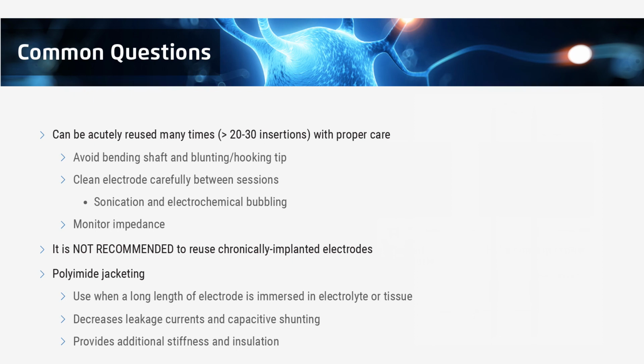Another benefit of electrochemical bubbling is it allows you to detect things like short circuiting as well as insulation damage. It's important to note that any exposed metal within the electrolyte that's subjected to this potential will create electrolysis. Thus, if any bubbling is seen anywhere but the very tip of the electrode, or at the recording site for LMAs, that means that the insulation may be damaged. If you see multiple channels bubbling, that means you've got a short circuit between channels. It's going to be a great way to diagnose issues between electrodes.